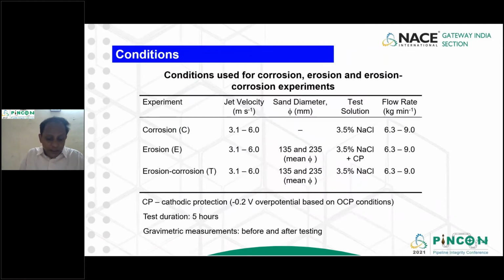Now I'll go into the experiment which I have carried out for this particular work. The first experiment is flow corrosion, where a liquid of 3.5% sodium chloride solution is passing through, creating a jet that impinges on the surface, with a velocity of 3 to 6 meters per second.